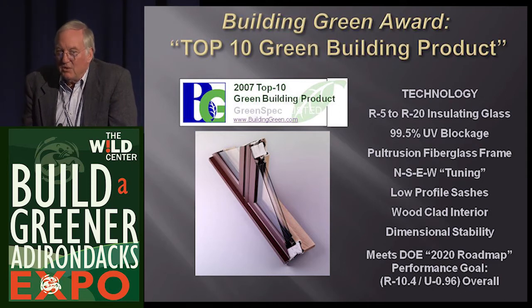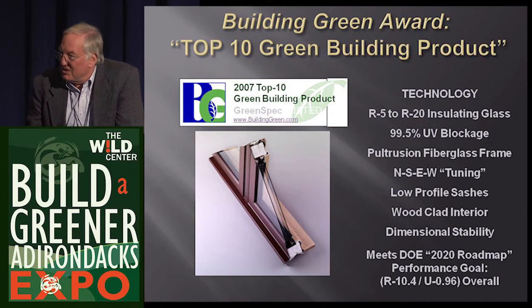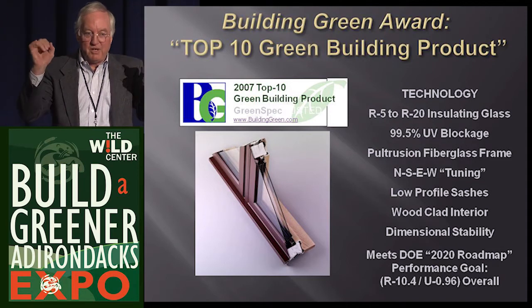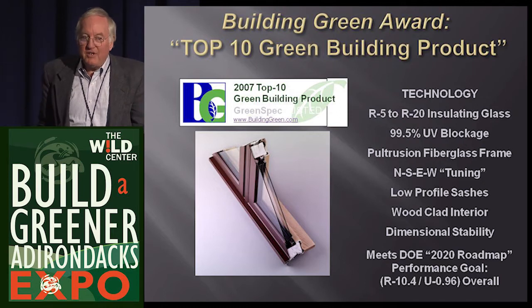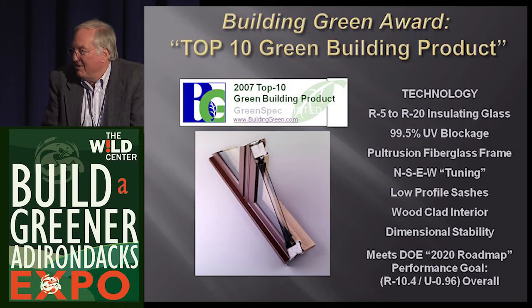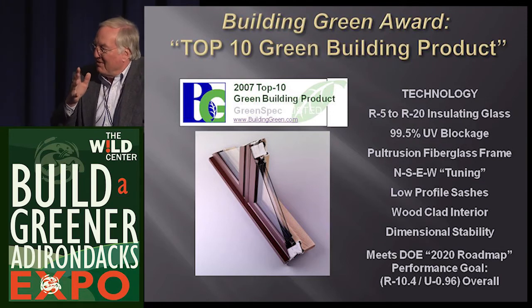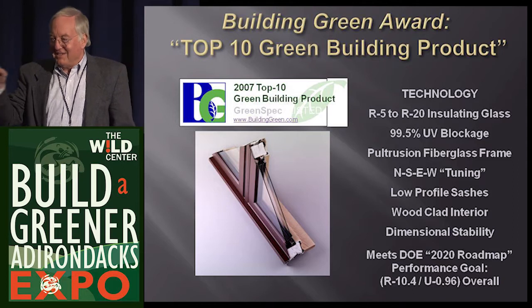The cross-section of the windows we manufacture is made of fiberglass - it's called pultrusion. For vinyl or aluminum sashes, you use pellets and extrude - pushing material out of a die. Fiberglass is pultruded using a three-foot mold with 600 spools of glass thread. Six tons of tension pulls it through; you pour 35% resin, 65% glass in the top, and out the other end comes continuous fiberglass - kind of a surfboard forever. Vinyl extrusion is fast, aluminum faster, but fiberglass goes very slowly.